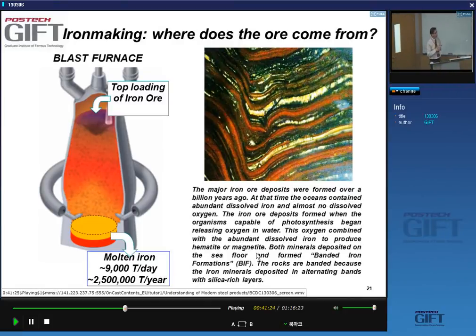form deposits of these oxides on the seafloor, and this ended up forming these banded iron formations, BIFs, where you have iron oxides alternating with silicates, and the very rich iron ores look like this. That's why in the blast furnace you need to reduce the iron oxide, and then also take out the silicates, which are originally in the ore. One will go to the slag, the other one will go to the liquid metal.